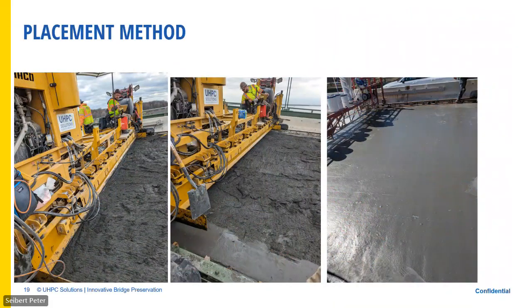Now this paver is a Gomaco product. Again, another piece of equipment specifically designed by us in conjunction with the manufacturer. And this is specific for UHPC, but is basically a modified slip form paver for thin UHPC applications. So it's got vibrating beams on the front and underneath to screed off and finish off the UHPC in place. And you can see these pictures on the left. And in the middle here, the UHPC out in front is kind of maintained at a level out in front of the paver, slightly high, so that the material can be pushed along and pressed down and struck off. And this picture on the right is the finished product out the back of the paver.